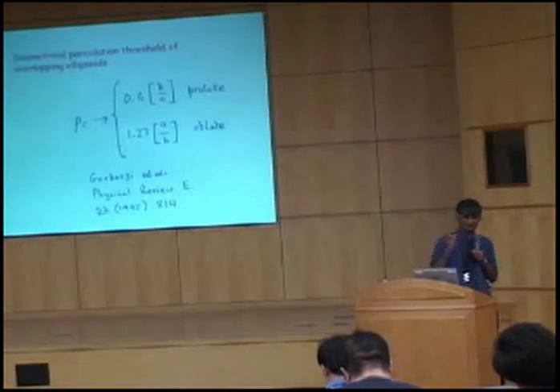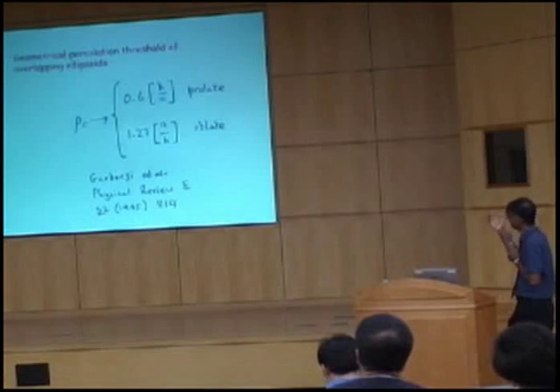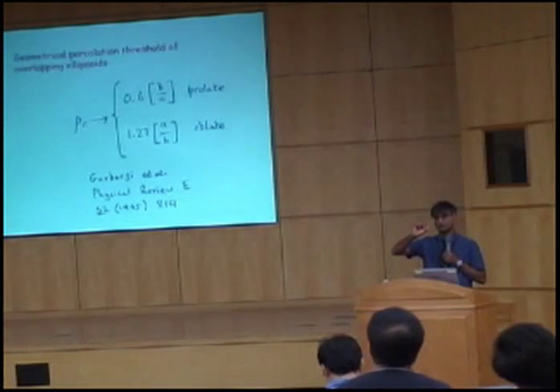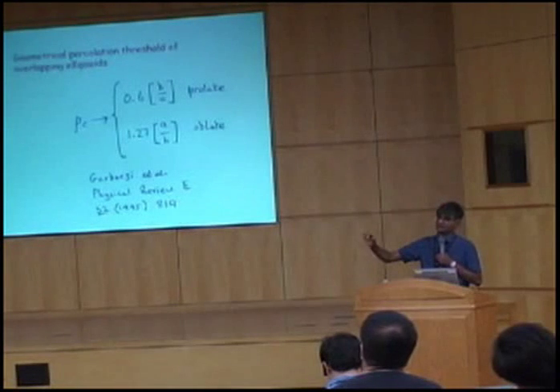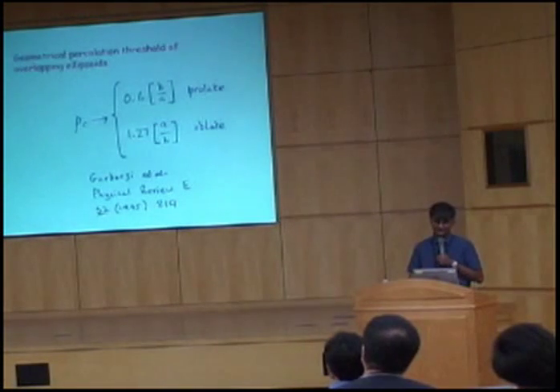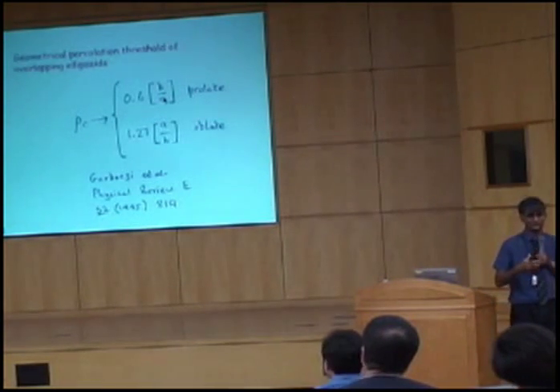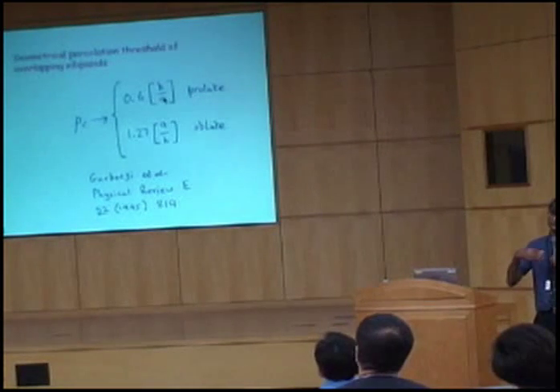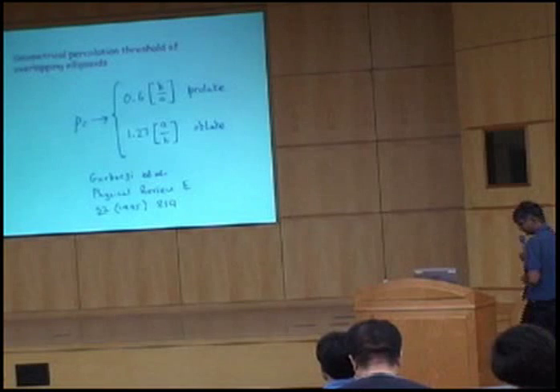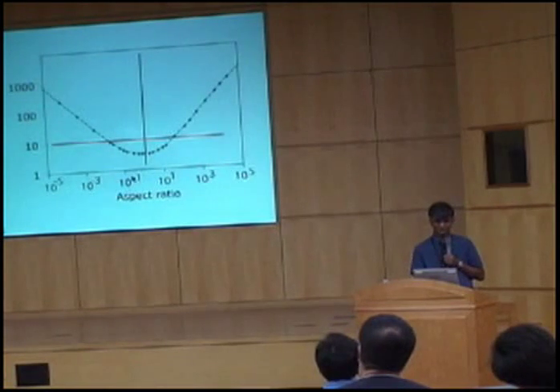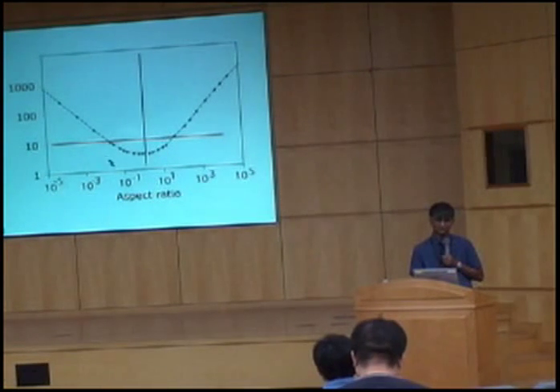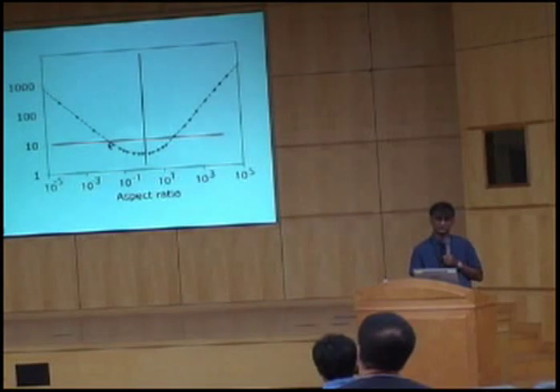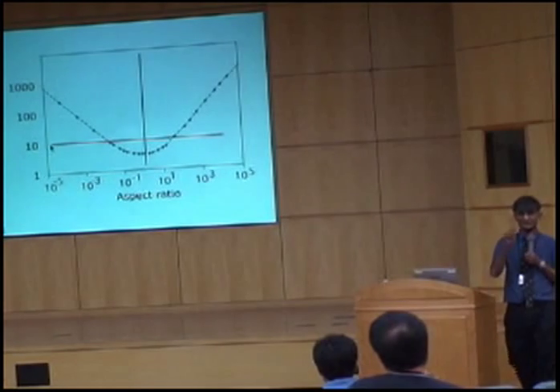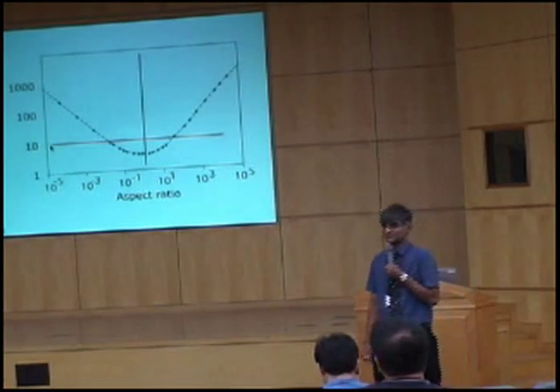Now, to prove that, we used percolation theory, which is already in the literature. You can see this is a paper from 1995, where we are looking at ellipsoids to represent the films of austenite. Okay? And this is just the aspect ratio of those ellipsoids. And you can work out from this at what fraction we will lose continuity in the austenite. So this is a plot of the aspect ratio of the films of austenite. And this is 1 divided by the volume fraction of the austenite. And you can see that for typical aspect ratios, we expect to lose percolation in the austenite when the volume fraction reaches about 10%. Okay?